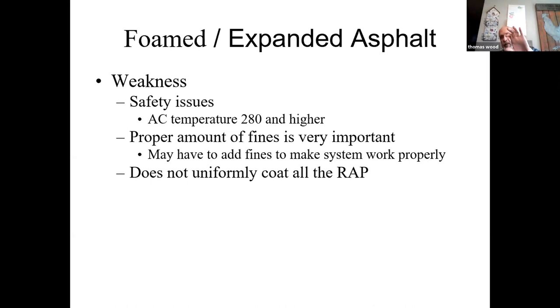But whether it's SFDR or CIR or cold central plant, and I don't see much foamed asphalt being used on cold central plant because the amount of time you have to place it is limited, you'll notice that it doesn't coat all the RAP. It does a real good job of coating the fines, but it leaves the bigger chunks of RAP uncoated. And I was a little concerned about that. I used to say, if you ran recycle through a hot mix plant at 20% or 30%, and you were getting chunks of RAP in new mix that weren't coated, I would have been concerned about that. And the people I was working with said, it's not that big an issue. And like I say, over the time, I'm modifying how big an issue it is to me.